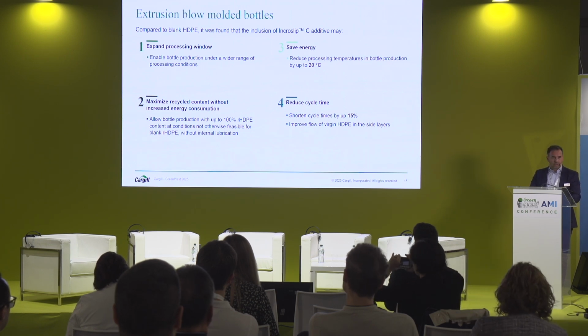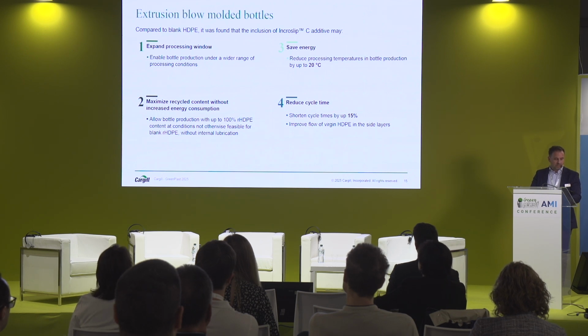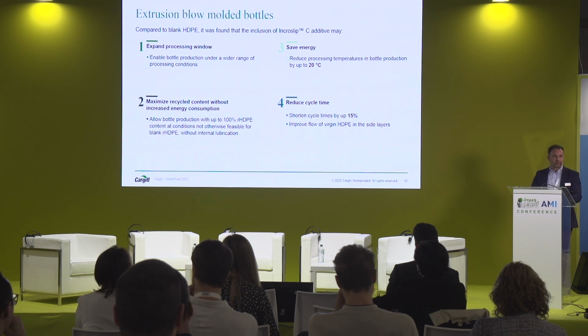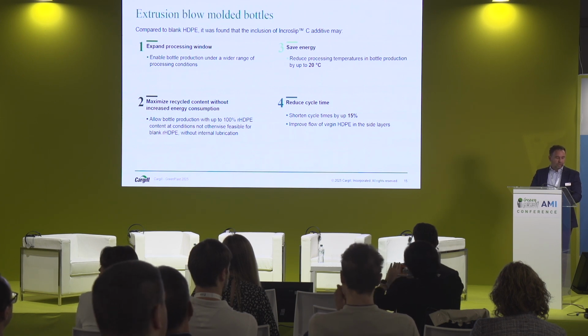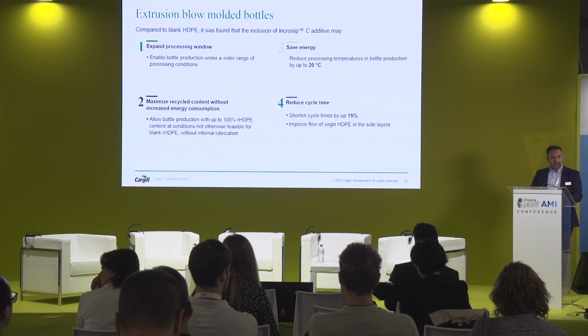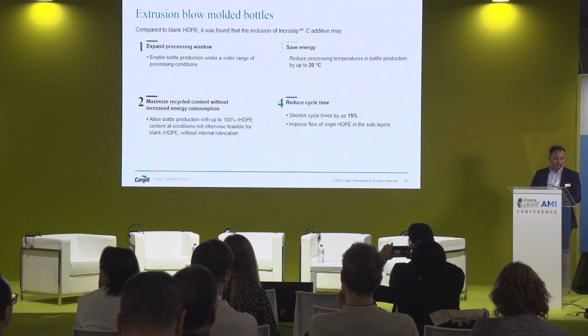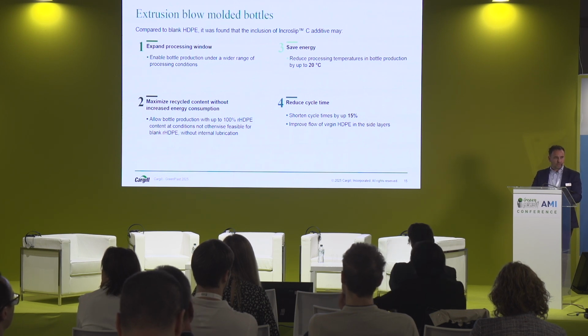So we can expand the processing window when we use the additive. We can use different conditions, especially extrusion speeds. We can save energy during processing by reducing the temperature 20 degrees or similar, and of course protect the polymer from degradation. We can increase the output rate, so we can make things faster. We have similar examples in film extrusion and other examples. And of course, we managed to increase the amount of recycled plastic in this formulation and even go up to 100% at very challenging conditions where blank material could not cope.